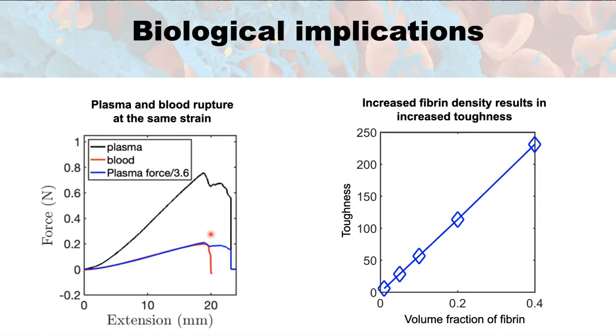We're also able to consider what would happen if the density of the fibrin network would vary, because patients with thrombotic conditions have an increased fibrinogen concentration, which means that in turn, they likely have an increased fibrin density in their clots or thrombi in comparison to a healthy subject. So again, by changing the volume fraction of fibrin in the model, we're able to see that increasing the fibrin density would result in an increased toughness, which again can help to have some potential clinical implications.